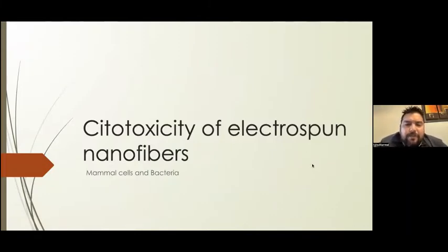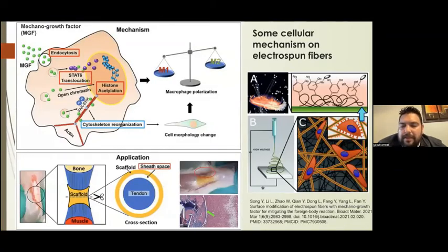After that, I will show you several works, several experiments that we have been doing with several postgraduate students. We always fabricate the fibers and then make a physicochemical characterization using SEM and FTIR. We also use TGA and DSC, meaning thermal characterization. And we also use cytotoxicity testing that I will discuss with you later. But the idea to load bioactive molecules on the fibers is in order to release these bioactive molecules and give some effect on the cells.